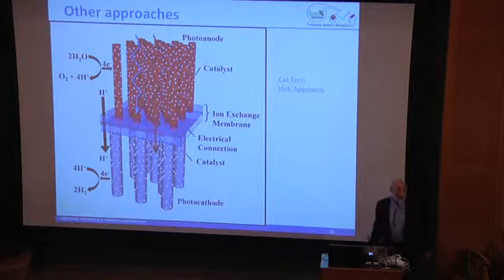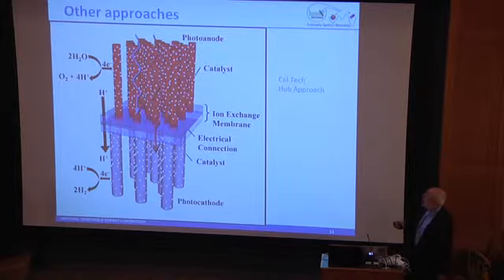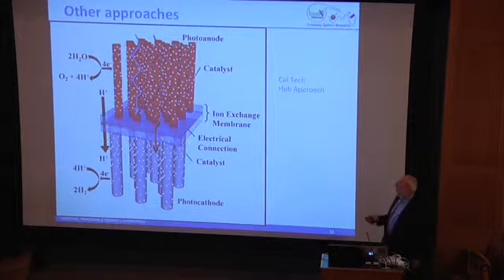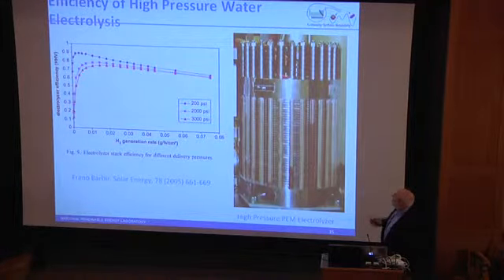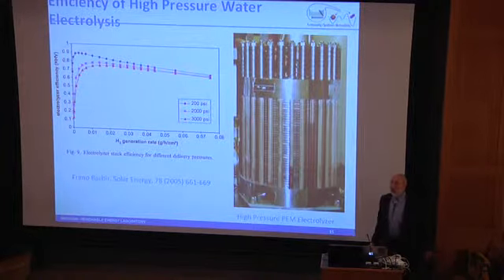The Caltech hub originally proposed a structure like this. They're now doing something different. This is very hard to realize, and it's very hard to realize in a practicable way. So you have to go back and think about it. This shows you a high-pressure electrolyzer and what the curve looks like. If you look at hydrogen generation rate versus the electrolyzer efficiency, at low rates you can get pretty substantial conversion rates on the order of 80%. As you go up in current, though, to where you really want to be, that falls off pretty dramatically.